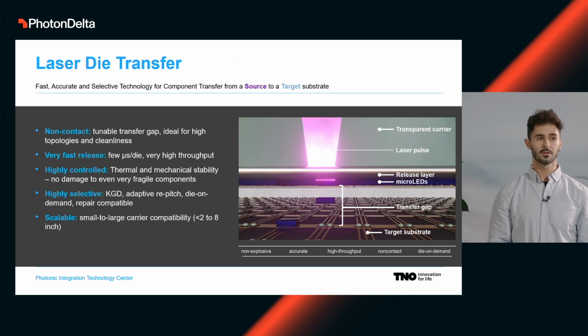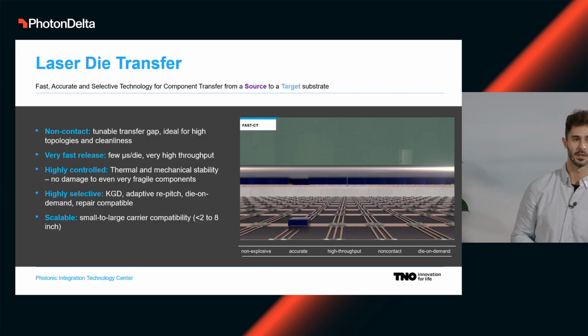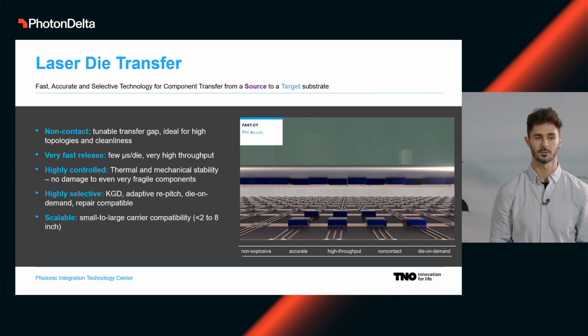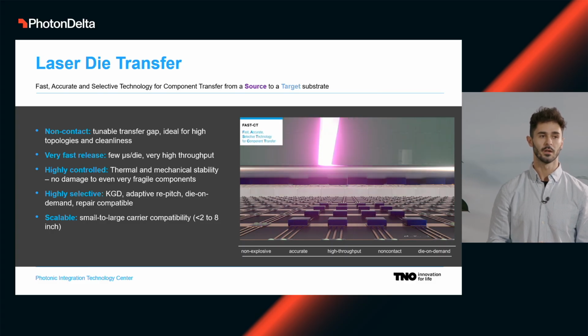Our approach to that is to use LIFT, or laser die transfer. Essentially, it's a technology that uses a laser shot to integrate components, effectively pushing a component from one substrate to the other when they're put in very close proximity within a transfer gap. I'm running the animation, so it shows how the process works. Of course, it requires an alignment between the two platforms.